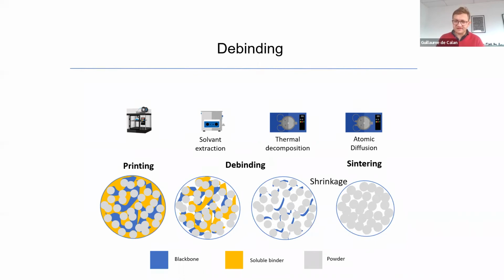And once you have done the thermal debinding, at that stage the part is extremely fragile. The particles are just holding together by mere contact forces, so if you just manipulate the part, you will break it. At that stage, you can't manipulate the part, which means when we do thermal debinding in a furnace and sintering in another, we actually put the part on setters, and we move the setters, but we won't touch the part, because at that stage it is extremely fragile. I hope that has answered your question.